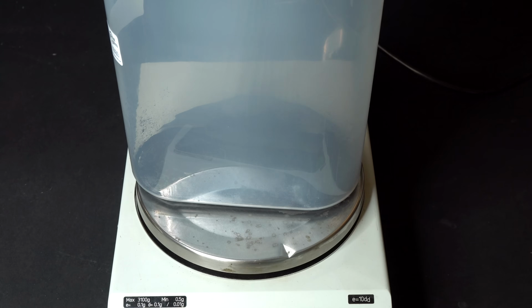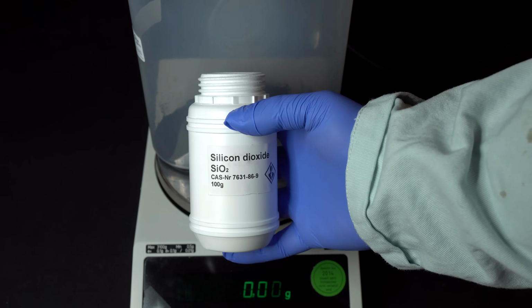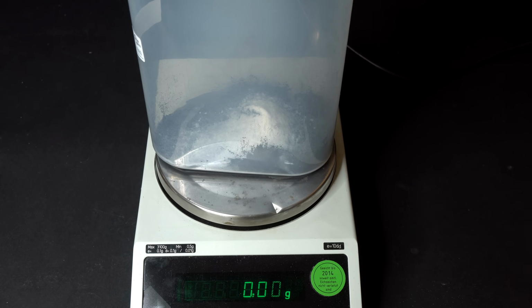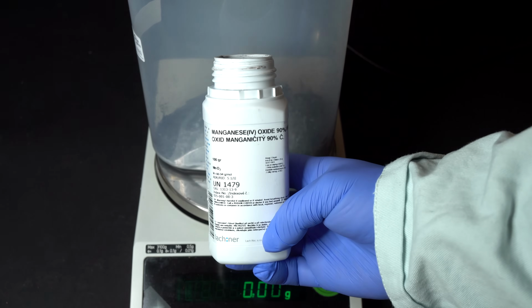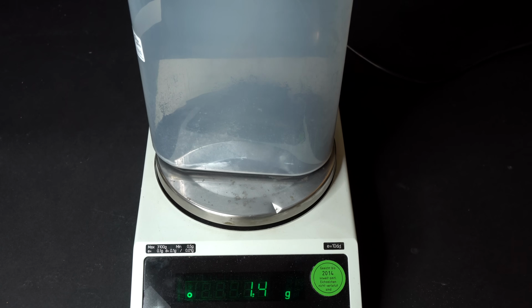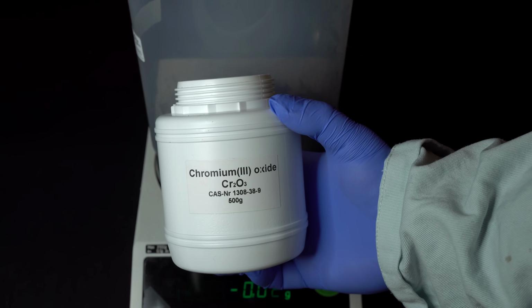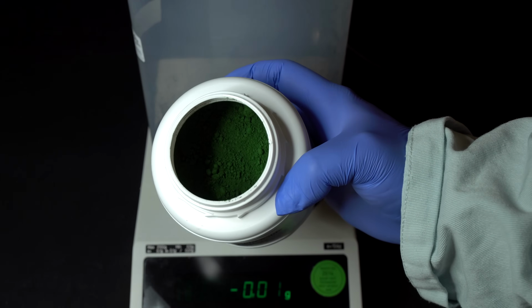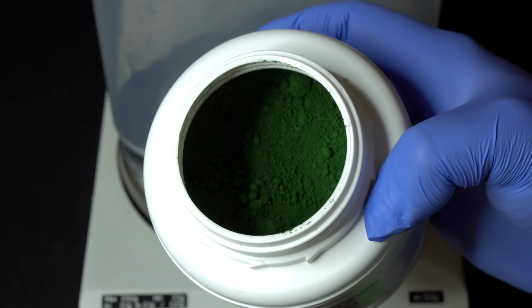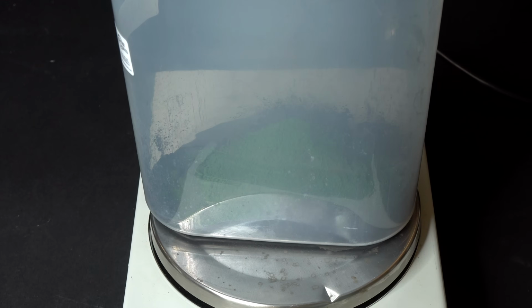First of all, I'm weighing 320 grams of my do-it-yourself magnetite powder into the stirring container, 5 grams of silicon dioxide in order to infuse the alloy with silicon, some manganese dioxide to harden the alloy, some nickel oxide and most importantly 50 grams of chromium oxide in order to give the obtained alloy anti-corrosive properties, because it is chromium that will form an oxide film in this alloy, protecting the stainless steel from oxidation.